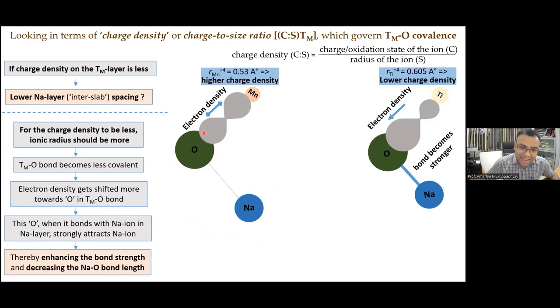The interesting point is that the other side of the same oxygen ion has a transition metal-oxygen bond, which is ionocovalent, and where a lot can be done by varying the covalency of this transition metal-oxygen bond. One of the things that can be done is altering the effective negative charge on the oxygen ion. If the bond is more covalent, then the electron density will be closer to the center of the bond, that is, away from the oxygen ion. Whereas if the bond is less covalent, then the effective negative charge on the oxygen ion will be larger because the electrons will be more polarized towards the oxygen ion and not towards the center of the bond.